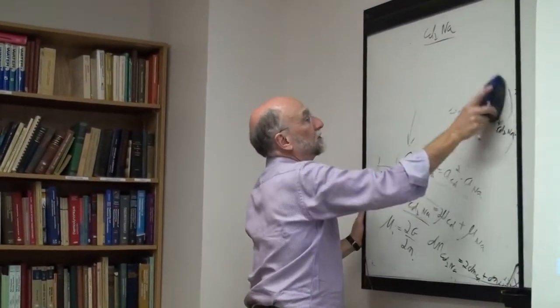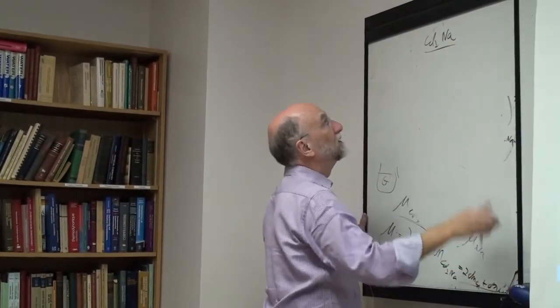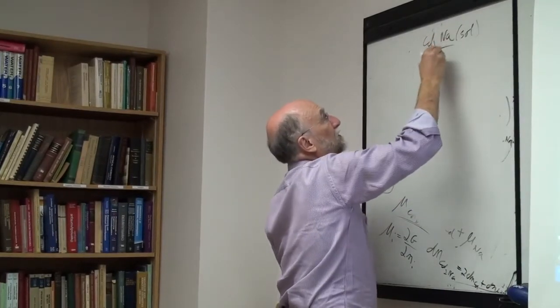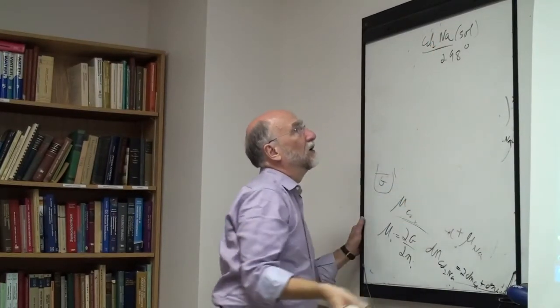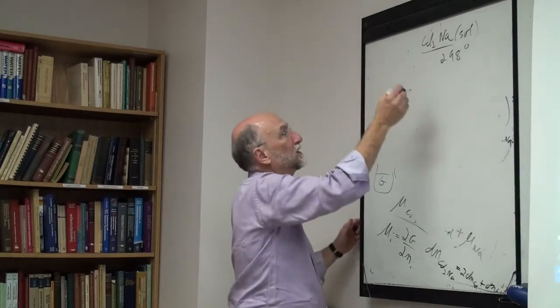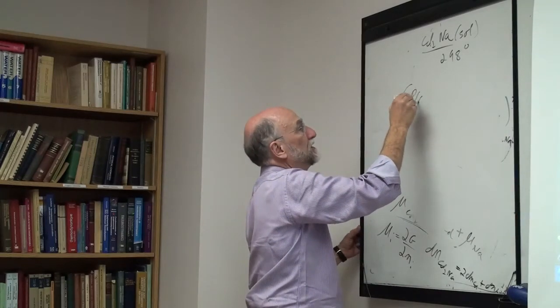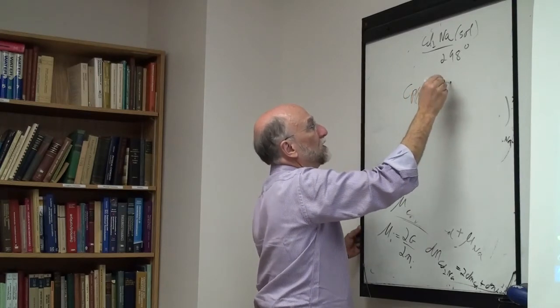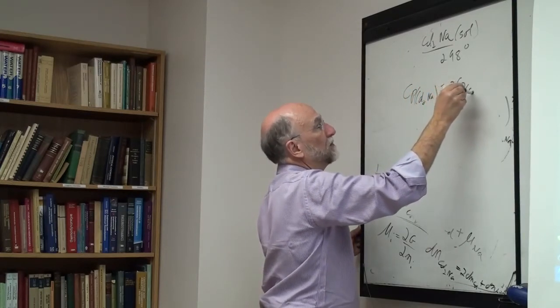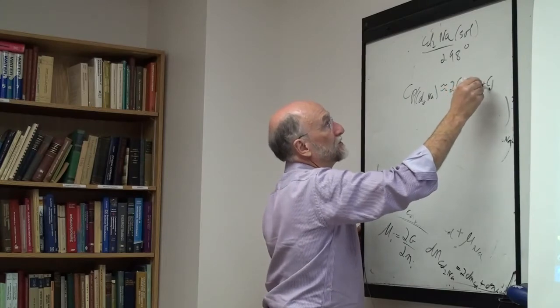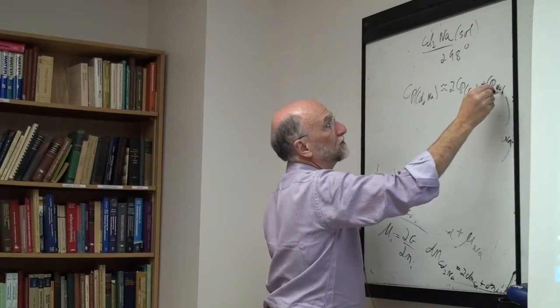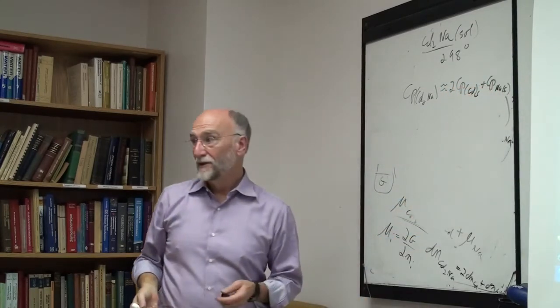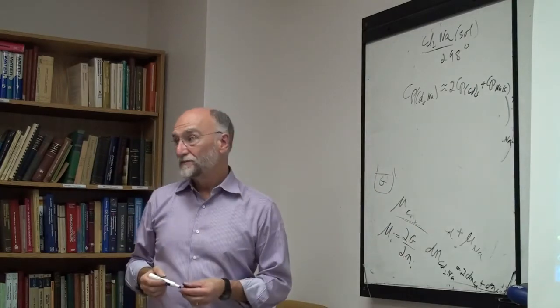we often make a solid compound, now we're talking about a solid compound at say 298 degrees. What sort of approximation? Say we don't know the heat capacity, well then we could say the heat capacity of Cd2Na is approximately equal to 2 times Cp of cadmium solid plus the Cp of sodium solid. That's the Neumann-Kopp rule. That's your first approximation.